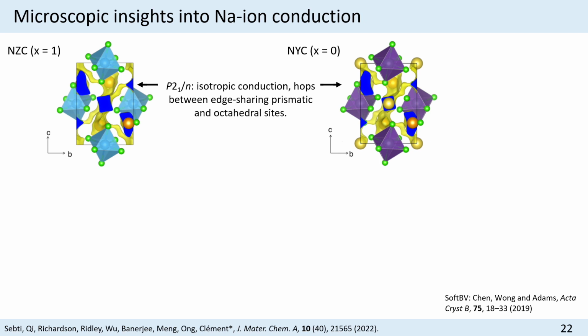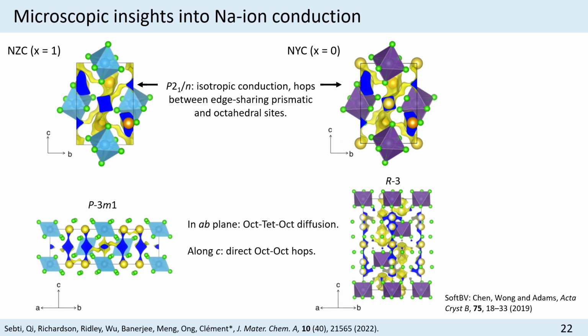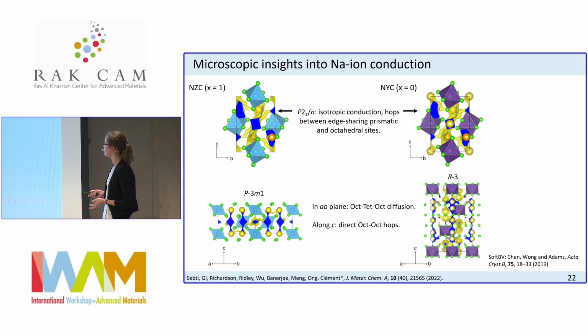So even if you have some pathways, this may not lead to diffusion because of the absence of vacancies. We also have two other polymorphs. For the NZC structure, we have this layered P bar 3M1 structure where you have much more anisotropic diffusion pathways. And for the NYC structure, you have this R bar 3 polymorph, again with anisotropic transport properties.